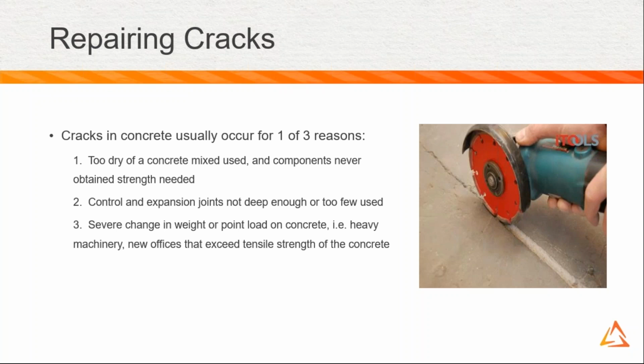Secondly, would be control and expansion joints, or what we call construction joints, were not put in deep enough, or too few were used to actually control the cracking or the expansion of concrete. And then thirdly would be severe changes or point loads on the concrete in your specific factory. And that could be for a myriad of reasons: heavy machinery, new offices that have been added that stress out the concrete, new racking with inventory that puts stress on concrete that it wasn't designed to handle that kind of point load, and it would cause a crack. So those are really what I feel, in my experience, are the three main reasons that concrete cracks.